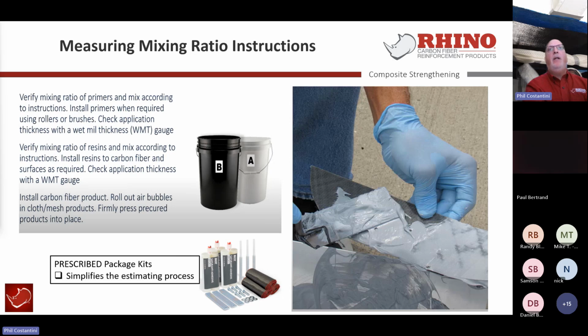And then the important thing is to pay attention to your mixing ratios as per our prescriptive method, and apply the proper thickness onto the actual material, and then install it to the structural element, rolling out all the bubbles, and then press it firmly against the structure, flaring back any of the excess epoxy over top of your carbon fiber laminate or dry layup application of non-cured fabric. So this is very important.